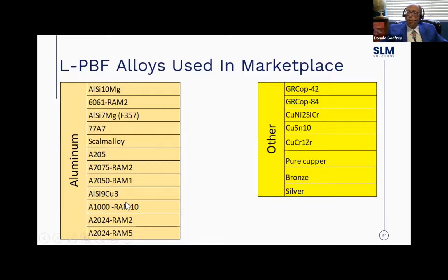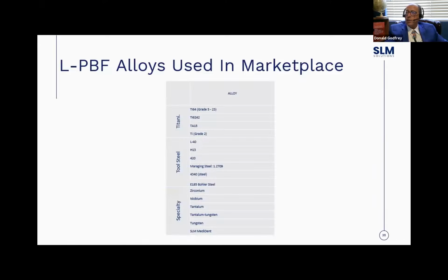But with any aluminum that you test, you have to test for oxidation. NASA is really big on GRCop-42. That's a new copper alloy that is being pushed hard by our friends at NASA. And then titaniums, tool steels, specialty steels. Tungsten is big in the space industry for satellites. And then 6242 is coming on because it's a higher strength titanium.